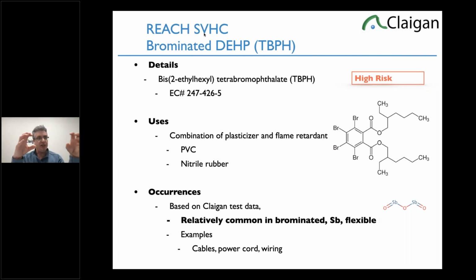So that's why they add antimony trioxide. The hydrogen reacts with bromine, creating hydrogen bromide. It absorbs some of the energy, but it's still overexcited. It would release energy back into the plastic, which creates more burning. And antimony trioxide comes along and reacts with it. Antimony is a much bigger molecule. It can absorb even more of the energy from the hydrogen bromide, and less gets kicked back into the plastic. And that's how a gas phase brominated flame retardant works. Pretty common, pretty useful. It's a great way to do flame retardancy. So when you have a brominated flame retardant, you're going to have antimony trioxide. It just doesn't work very well without it.